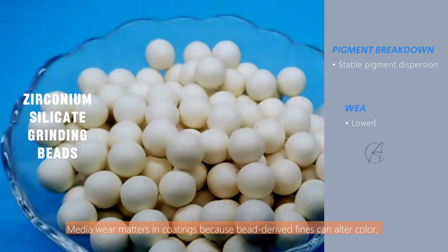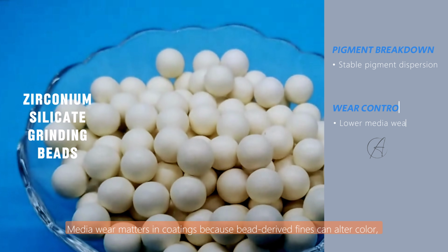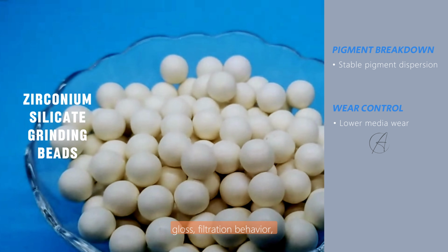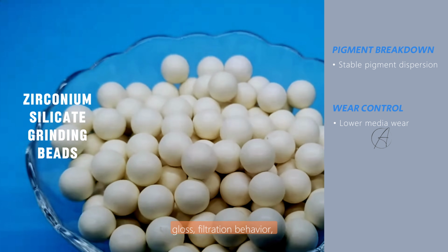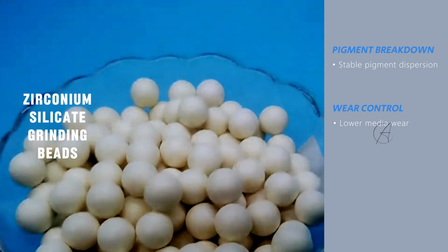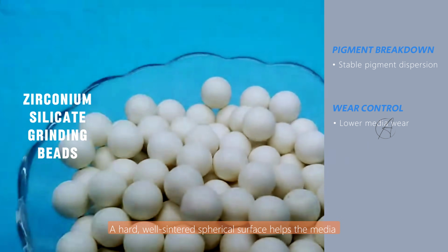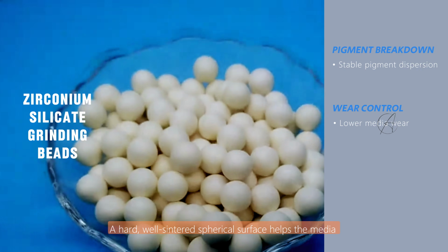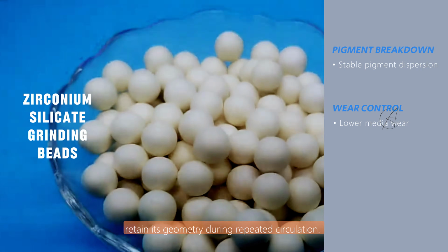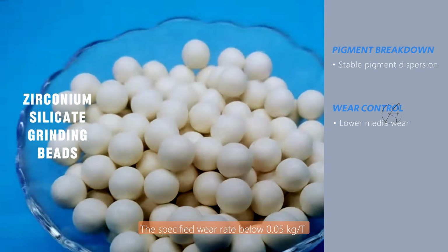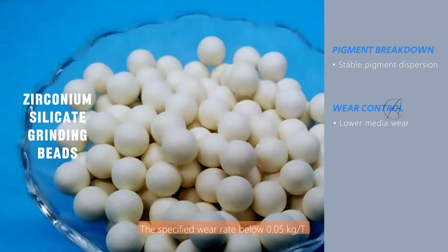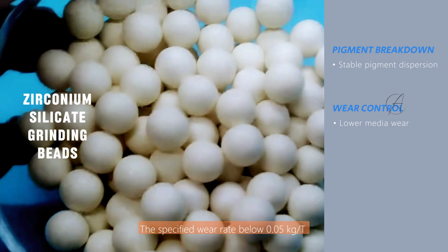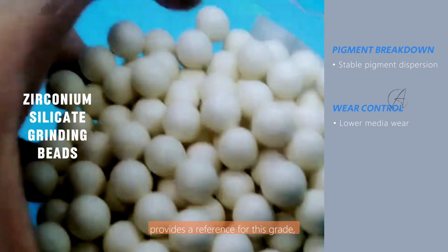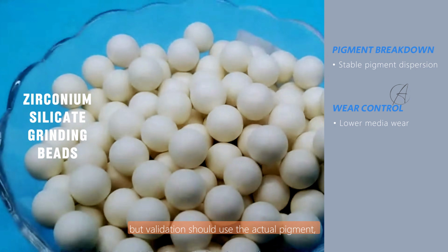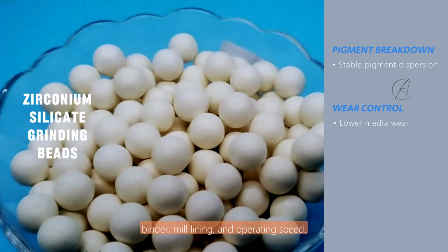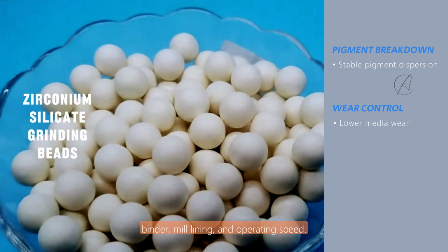Media wear matters in coatings because bead-derived fines can alter color, gloss, filtration behavior, or downstream cleanliness. A hard, well-sintered spherical surface helps the media retain its geometry during repeated circulation. The specified wear rate below 0.05 kilograms per ton provides a reference for this grade, but validation should use the actual pigment, binder, mill lining, and operating speed.